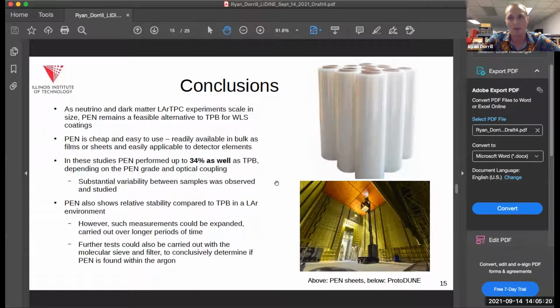So the conclusions to take away here are that PEN is potentially a viable replacement for TPB. The performance varies. In this study, it performed about 34% as well as TPB, although some recent studies by Marcin show it may perform even better than that. There was variability between the samples, so how you prepare them and attach them to your surfaces or other backgrounds is very important. It also seemed to show relative stability, although we would like some more measurements with that in the future.